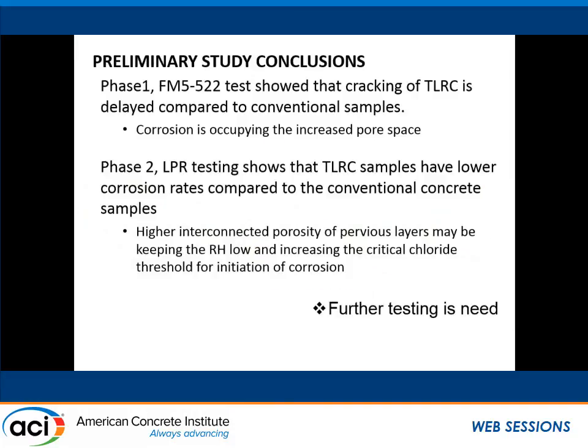So this is a special interest. Off the field, we said, hey, let's try some stuff on the side, and we made some lollipop samples, and it seems to help in lollipop samples. We're doing some linear polarization. Seems to be better. We're getting ready, before Thanksgiving, to place some very large reinforced concrete beams with the 2-layer system, and we're going to break them to look at bonding behavior, but it's kind of a side piece based on what George has shown us.